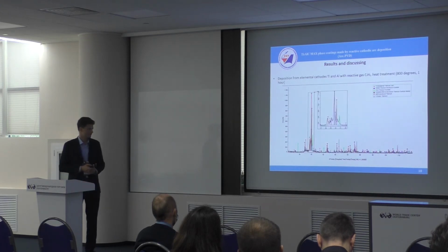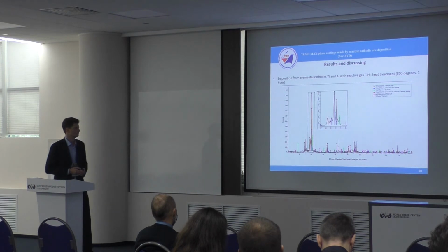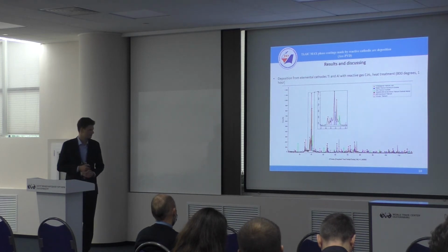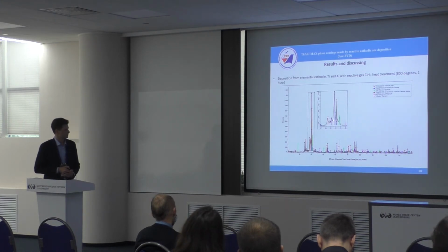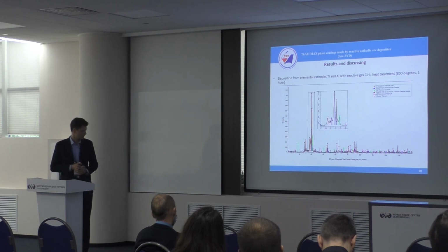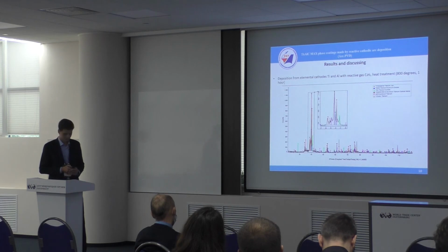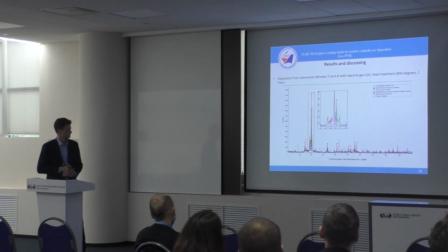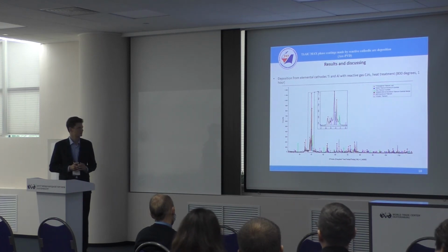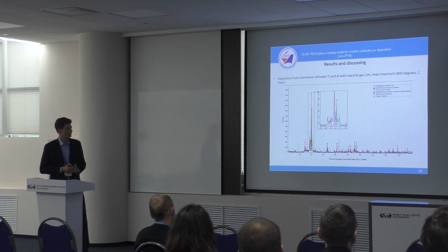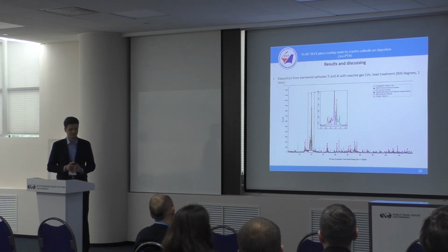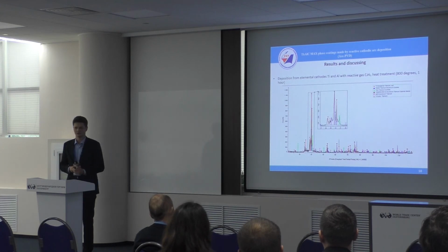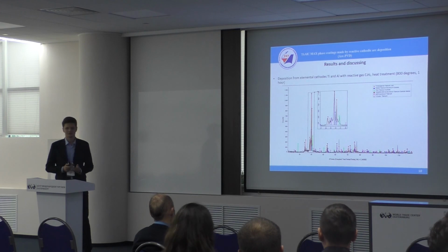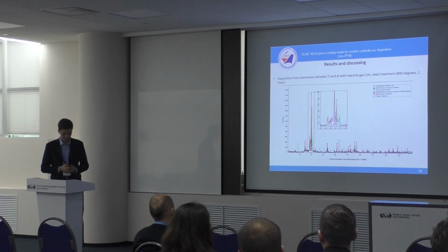But the situation changed dramatically when we used annealing. You can see much more crystallinity, and you can see blue peaks of our desired MAX phases, as well as some titanium carbon peak. But what is most interesting in this picture is the biggest peak with excellent matching, about 95%. It's titanium aluminum carbon nitrogen, a MAX phase carbonitride. It was quite surprising for us because the design of experiment did not involve nitrogen. One explanation that I can provide is that the vacuum furnace used for annealing was not vacuum enough. But we will examine it later.